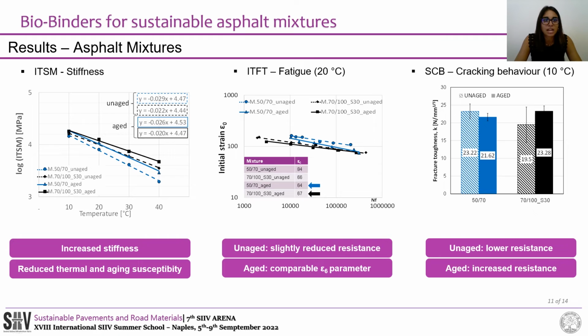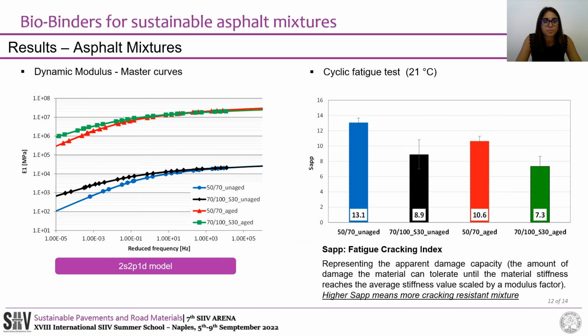A slight reduction in fatigue life appears in unaged conditions, even if perfectly comparable performances emerged in aged conditions, as shown by the epsilon 6 parameter. From the cracking analysis, the lignin-based asphalt mixture seems to improve the aged performances, despite a lower resistance is experienced in unaged conditions. The same findings in terms of stiffness and aging susceptibility are also confirmed by the master curves